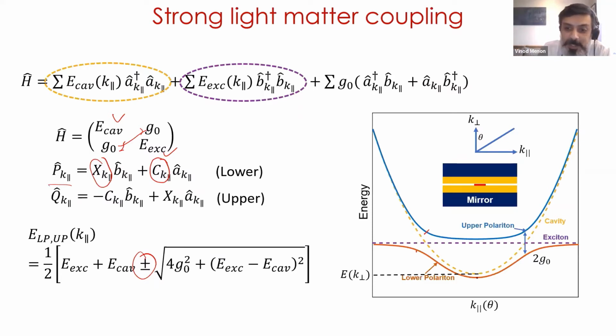Or in other words, if I take this branch of the lower polariton and ask what this is, it is a hybrid state of light and matter. But what is the contribution of my matter component here, and what is the contribution of my photon component? Well, xk will tell you the contribution of the exciton in the branch, and ck will tell you the contribution of the photon. What you see right away is that as I go to larger and larger wave vectors, the system becomes more exciton-like. Or in other words, ck goes down and xk goes up. If you look at the upper polariton, it's the exact opposite. So you can see how the contributions of the material excitation and the photon excitations get shifted as you go in in-plane momentum. And this is something that is useful to look at nonlinear interactions and so on.